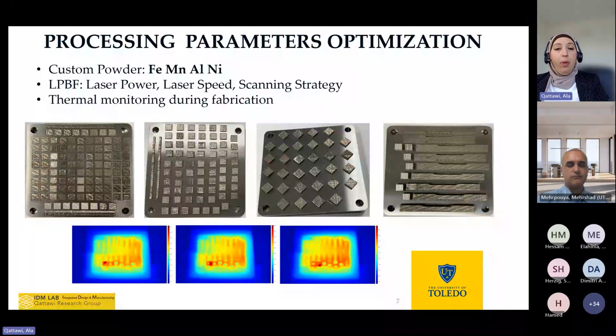So we started with a laser powder bed fusion machine with a heated plate, as you can see, that is not heated. Another technique that we introduced in the IDM lab is that usually we lay the powder and then we have a laser that scans lines or whatever the pattern is, and then creates the final component we need. Because of the differences in the thermal energy that's dispersed across the part, we have huge residual stresses across the component and the material, because the plate is actually cold, and the powder is the material that's getting all the heat from the laser.